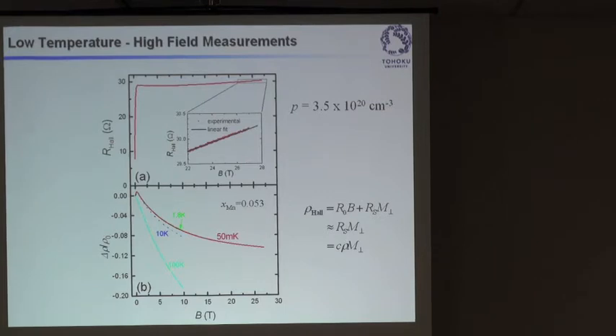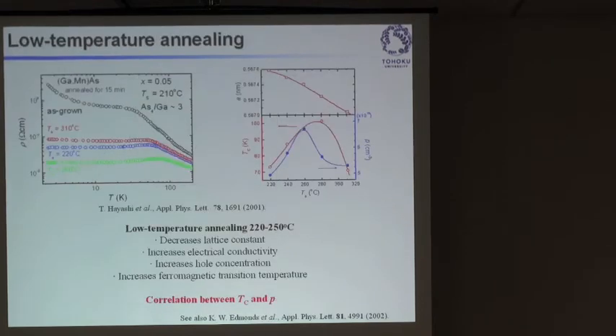So that was a question we had at the very early stage of understanding the material. The answer came from many directions, but the first hint came from low temperature annealing. We have grown gallium manganese arsenide using low temperature MBE. But after growth, you anneal at the very same temperature outside the chamber again, this gallium manganese arsenide.